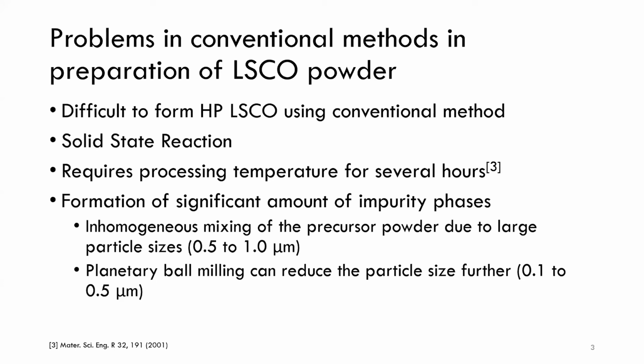These impurity phases are possibly a result of inhomogeneous mixing of the precursor powders due to large particle sizes. The particle size from a mechanically milled precursor powder can only go down to around 0.5 to 1 microns in diameter. One can further decrease the particle size of the precursor powder by using a planetary ball mill. In this way, milling can only produce particle sizes that are about 100 to 500 nanometers in diameter, depending on the milling parameters.